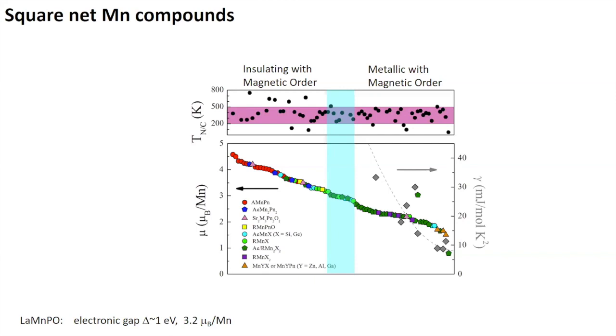The plot that I'm showing you here is an organizational scheme where we went to the Inorganic Crystal Structure Database and collected all the manganese-based compounds that formed in the same structure types as the iron pnictides. I've rank ordered them here in order of the moment per manganese ion. There are two kinds of manganese square net compounds, and you can see on the left that the manganese moment can approach 5 Bohr magnetons per manganese, and in this regime you have magnetically ordered insulators.